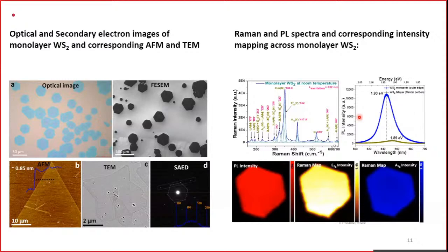Especially in the photoluminescence, if it is a bilayer instead of a monolayer, you can see the effect here. The blue color essentially shows the emission at 1.93 electron volts for the monolayer. But the moment you have the addition of one more layer, just a 2 layer, you will see there is a small shift in the peak position.